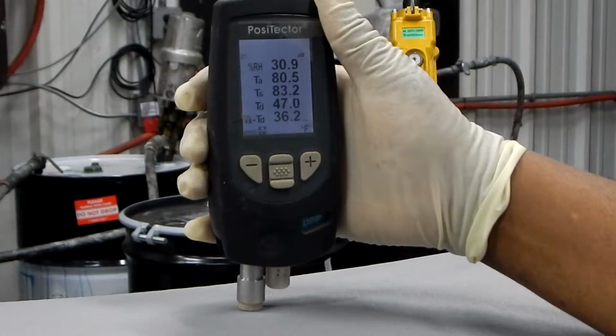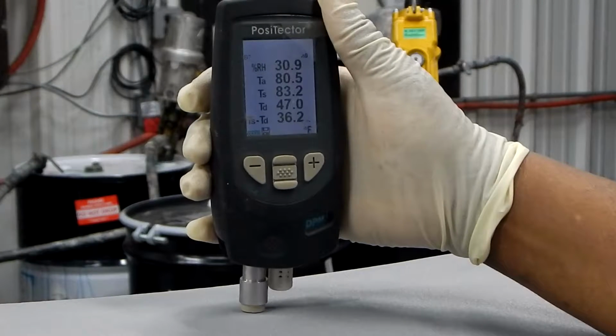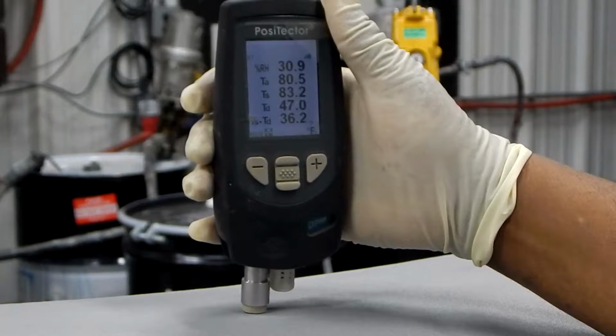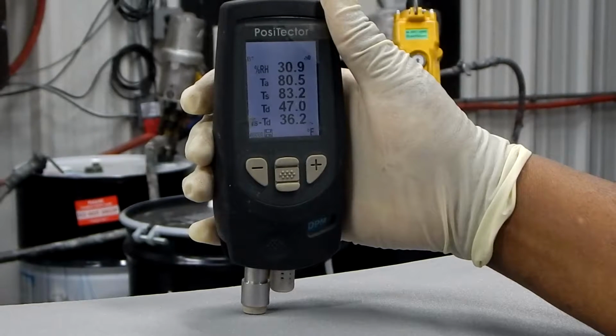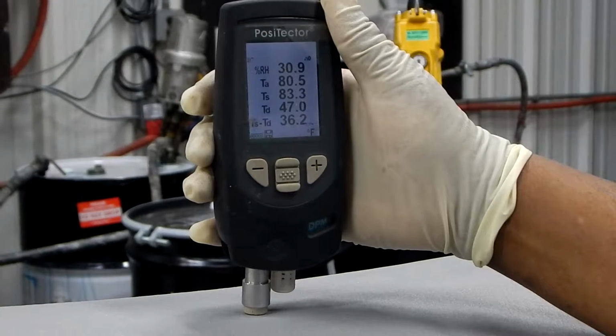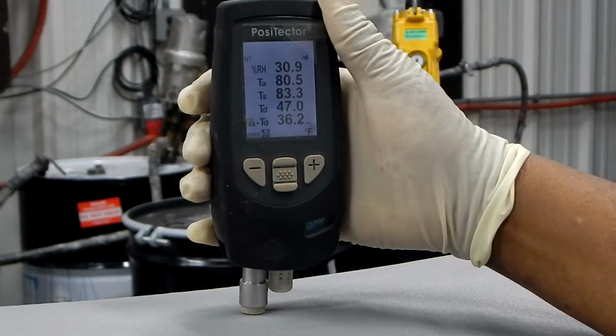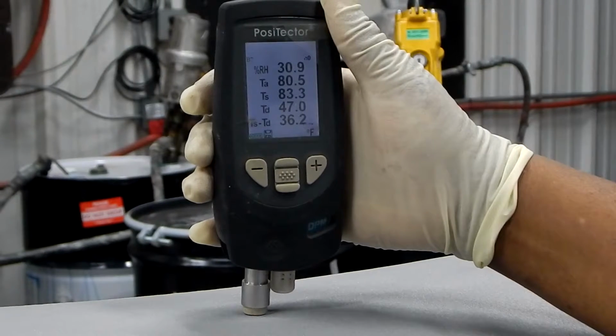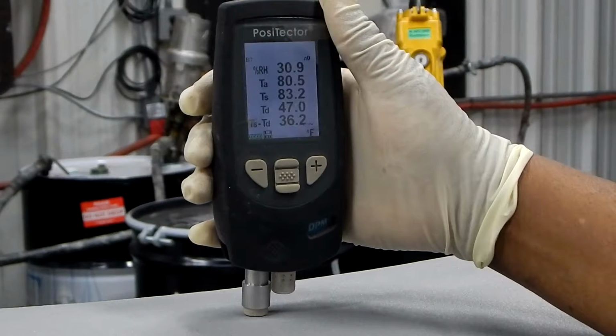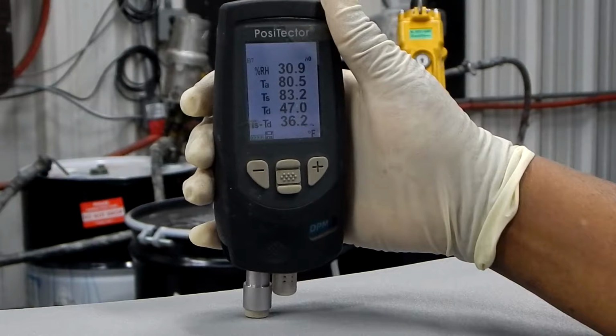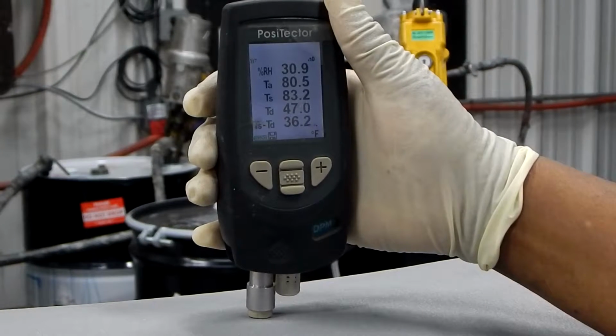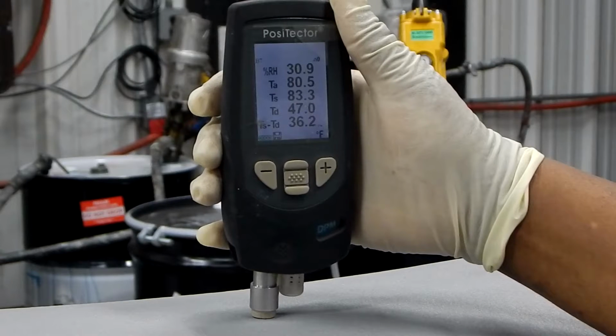Step 10. Verify the dew point. This step is to measure the dew point and to ensure that the coating area is a minimum of 5 degrees above the dew point. To get this measurement, view the TD reading. Verify the coating area is at least 5 degrees above the dew point. Record in the daily QC log. If it is an appropriate temperature, move on to the next step.